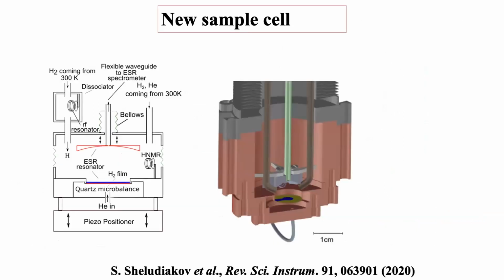So we built a special cell for this. This cell allows moving the distance between the spherical mirror and the flat mirror in two ways. First, we have bellows which can change the frequency by about 10 gigahertz. We also have a piezo positioner with bellows for fine tuning the frequency by half a gigahertz.